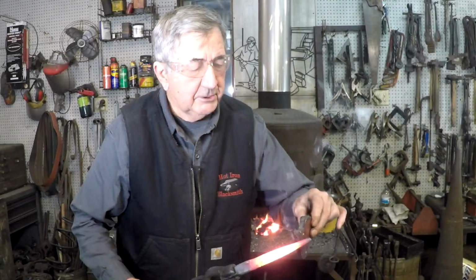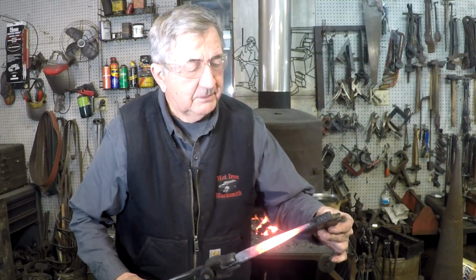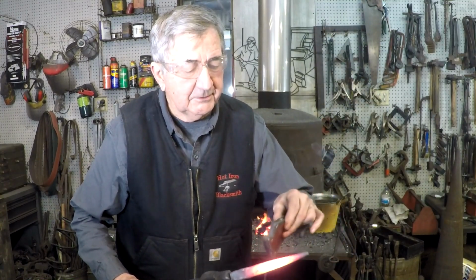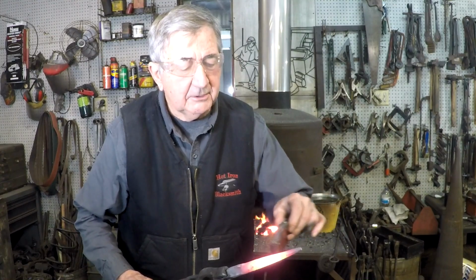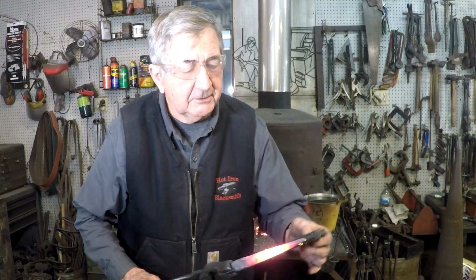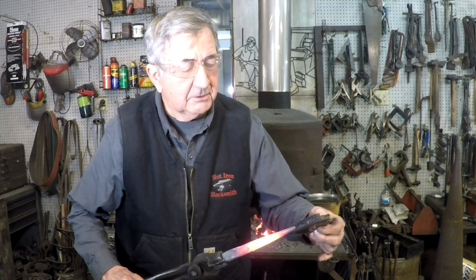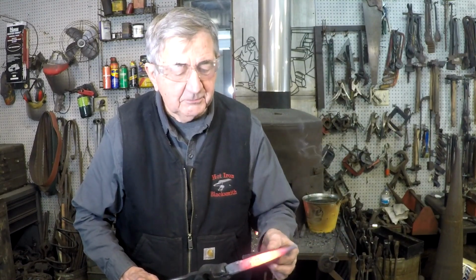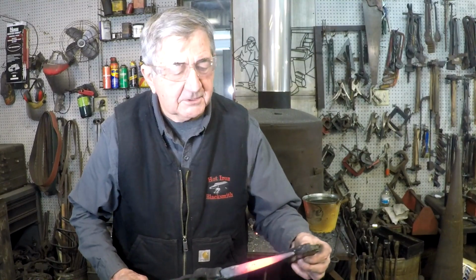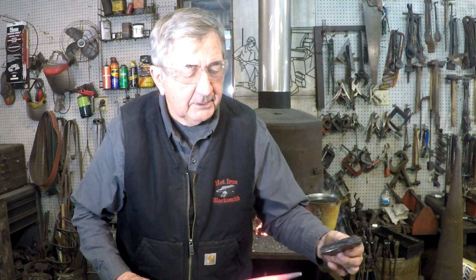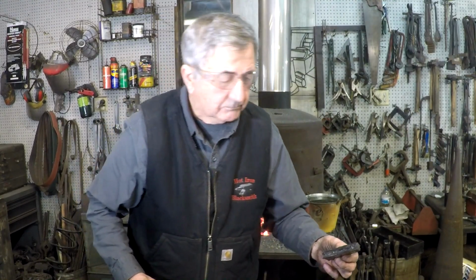So this is the round punch, and the very end of this is maybe a little magnetic, but letting the heat come from the center out here, the center part is definitely not magnetic. So we're okay, and this will allow this to anneal down. And I'll lay it off to the side and let it come down to 300 degrees.